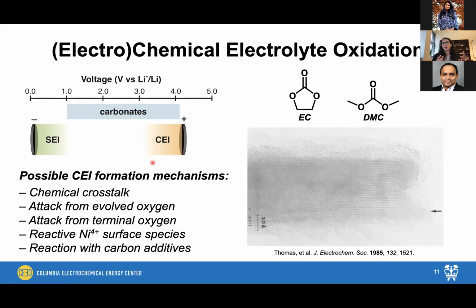As we move from a cobalt-rich composition like lithium cobalt oxide to something that is more nickel-rich like NMC811, we're actually changing the chemistry of those terminal oxygens. And we are also changing the reactivity of those surface oxygens. So we are increasing the nucleophilicity there. So it's also possible that those surface oxygens can attack the carbonate molecules. So it might be a chemical mechanism of decomposition that's causing the buildup of this interface layer on the surface of our active particles as well.